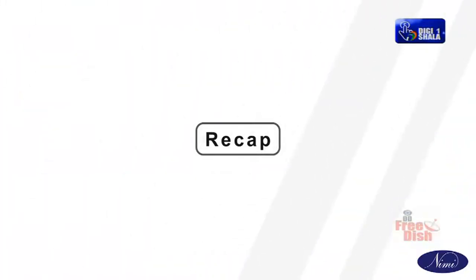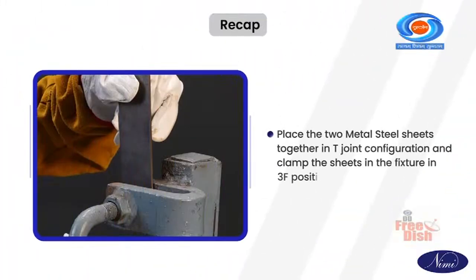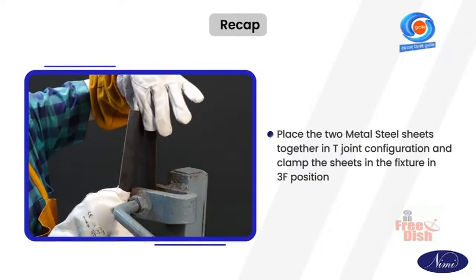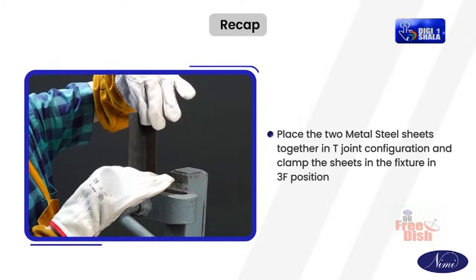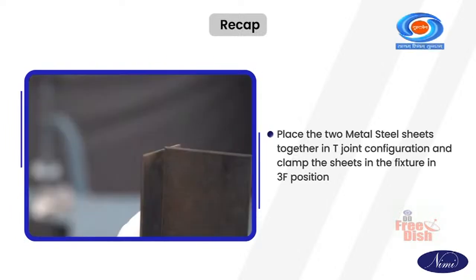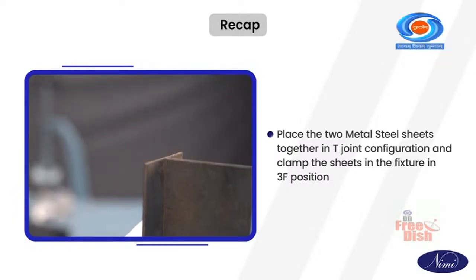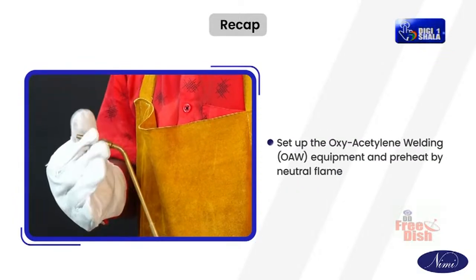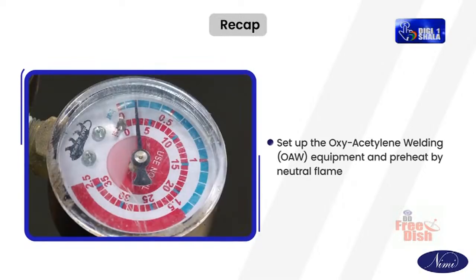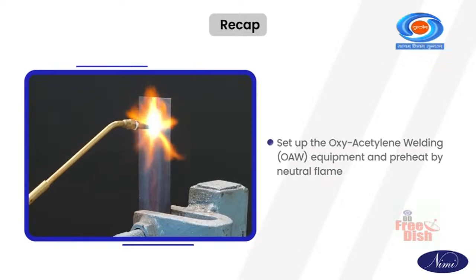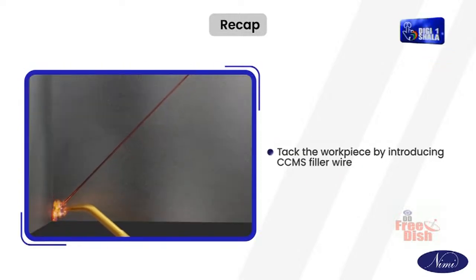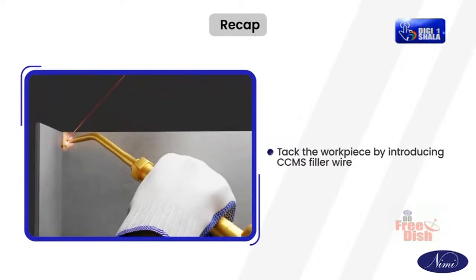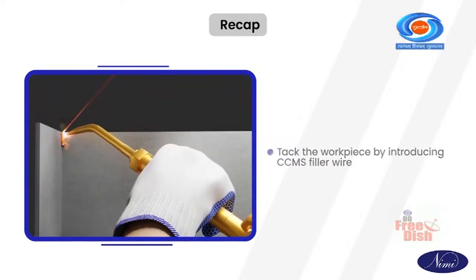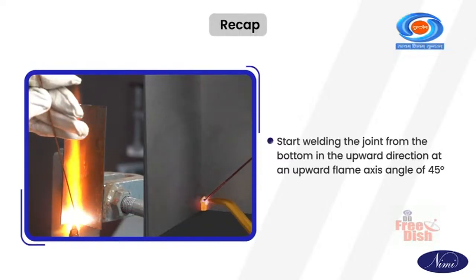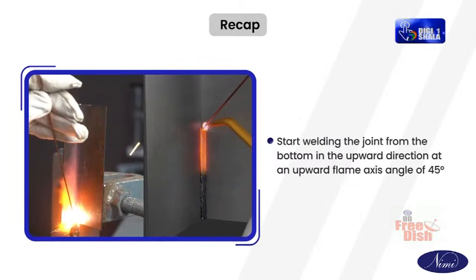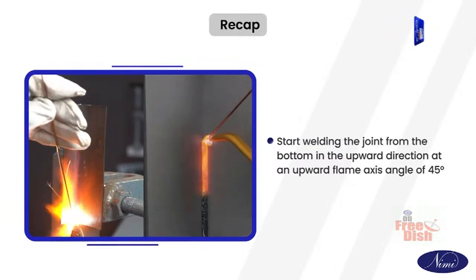Let's recap the key points discussed. Place the two metal steel sheets together in T-joint configuration and clamp the sheets in the fixture in 3F position. Set up the oxyacetylene welding equipment and preheat by neutral flame. Tack the workpiece by introducing CCMS filler wire. Start welding the joint from the bottom in the upward direction at an upward flame axis angle of 45 degree.